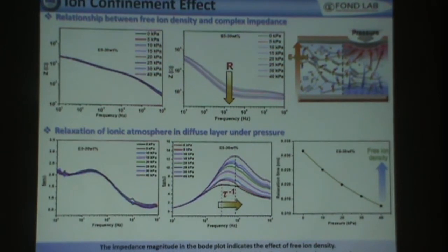This indicates that more ions are being pumped as the pressure increases, and this leads to the reduction of the bulk resistance in the sample with chlorine functional group. You can also see that the charge relaxation frequency shifts towards a higher frequency, which also indicates that more ions are being pumped, and this increases the ion dynamics in our system.